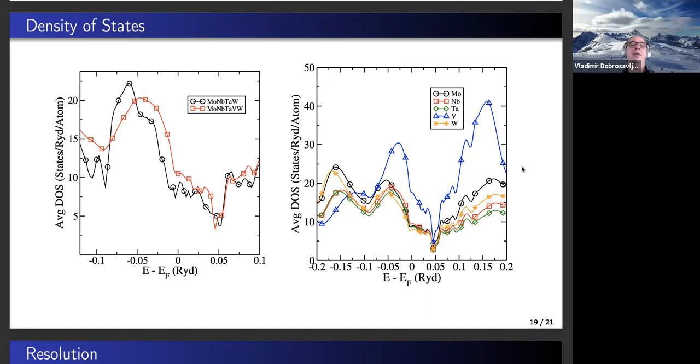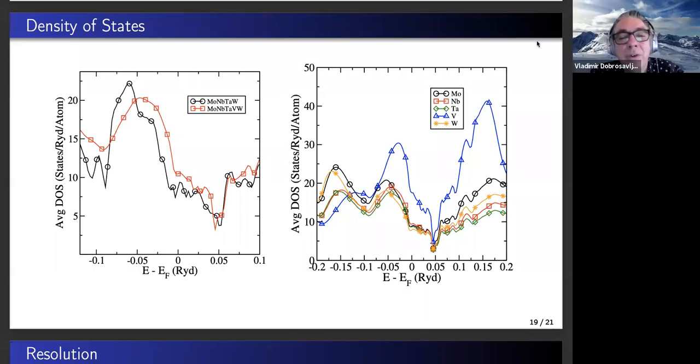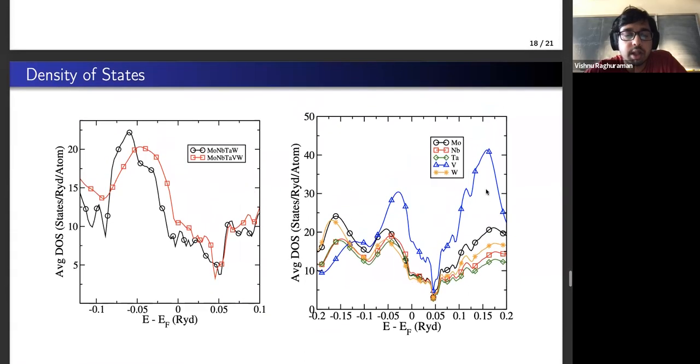I think the average bond length will change, obviously, with the mixed elements. But the question is, how is the variance in the bond length affected? I've been told that in many alloys, high entropy alloys, the bond lengths are remarkably uniform throughout the crystal, even though you have random concentrations of different elements. I've been told that this is one of the mysteries. Anyway, I guess we would have to do some sort of supercell calculations.